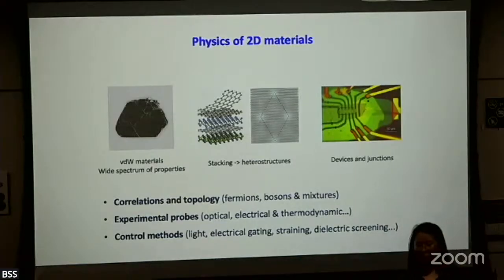And thermodynamic measurements, I'm talking about chemical potential, magnetization, polarization, entropy, specific heat. Those measurements are extremely challenging. And the reason is because we are dealing with one atomic layer or few atomic layer materials, and you have a micron square, roughly, the size. And you just don't have too much material to work with if you want to get thermodynamic properties. And often they are embedded in a bunch of other structures, and those can dominate your signal. So those are the difficulties.